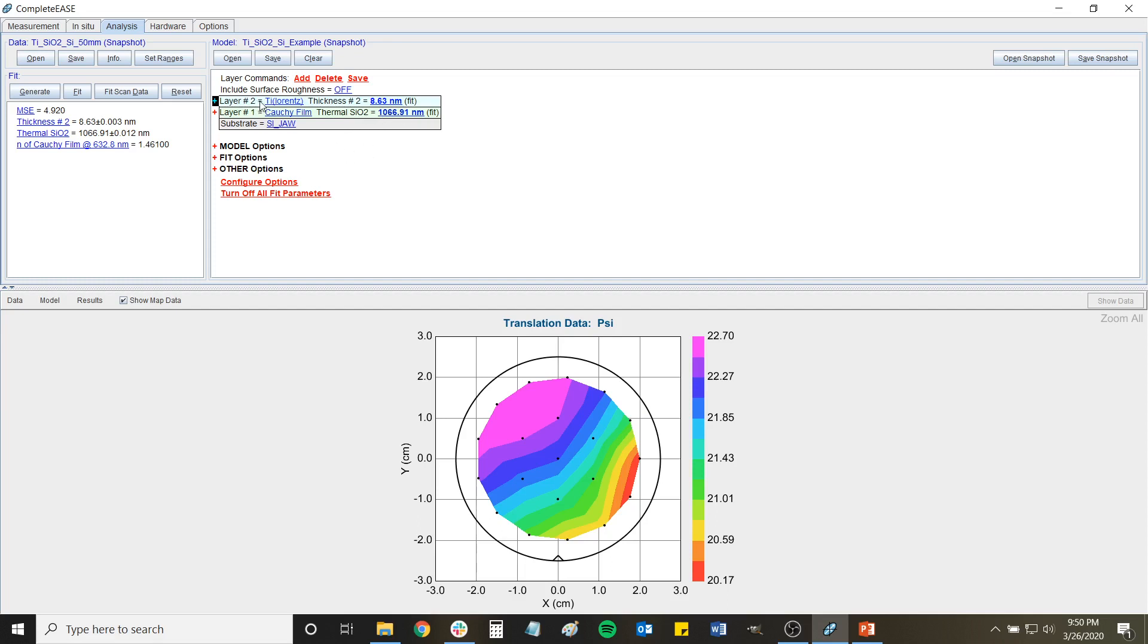And then you would deposit a thin layer of the metal on top. Now when I say thin, I'm saying something that's thin enough to absorb some of the light that passes through it, but certainly not thin enough to absorb enough to stop multiple reflections. So you want the light to go through the metal and then through the dielectric beneath it and then bounce off the substrate.